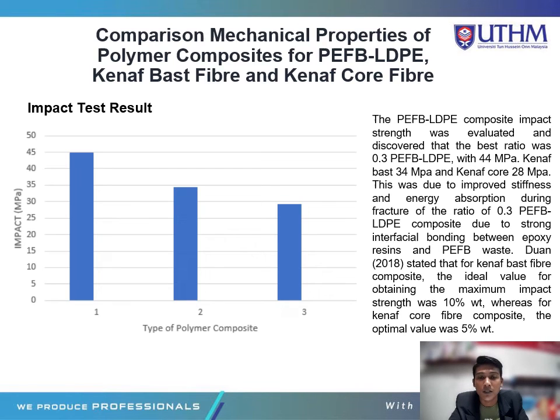Duan 2018 stated that for the Kenaf bast fiber composite, the ideal value for obtaining the maximum impact strength was 10%, whereas for the Kenaf core fiber composite, the optimum value was 5%. But with the 10% of the Kenaf bast and the 5% of the Kenaf core, PEFB LDPE still gets the higher impact test result.